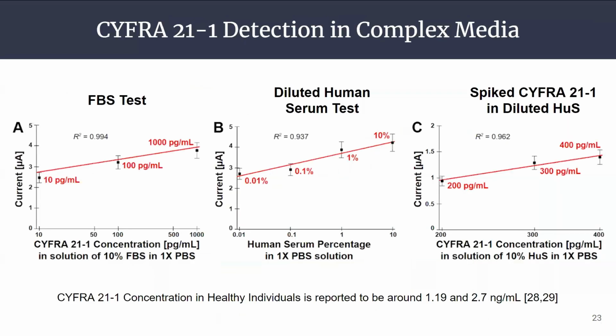To evaluate the sensor viability in a clinical environment, it was tested under 3 different circumstances. First, it was tested by adding a known concentration of CYFRA to fetal bovine serum because of its natural lack of CYFRA. Then we tested with serial dilution of human serum with no added CYFRA. And after that, we spiked a known concentration of CYFRA in diluted human serum. We evaluated the sensor's performance in these 3 scenarios, again achieving highly linear behaviors and accurate models for CYFRA concentration prediction.